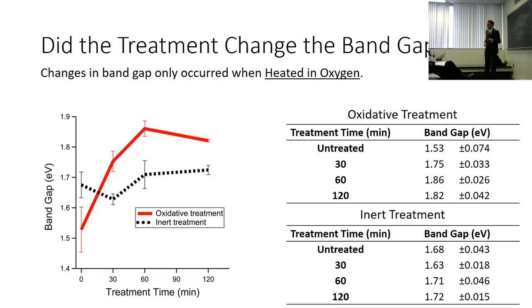This is where I learned the second thing about professors: they're usually right, you should listen to them. Because heating up in an inert environment doesn't change the band gap. You'll notice that the initial band gap is different—these were two different samples, the red line and the black line. So back to our other mystery, why different samples have different band gap. But heating them in oxygen changes the band gap, while heating them in inert doesn't change the band gap.